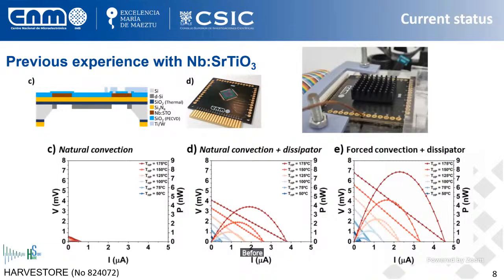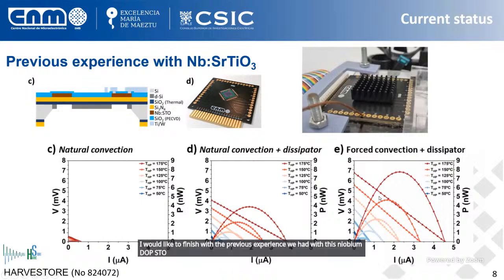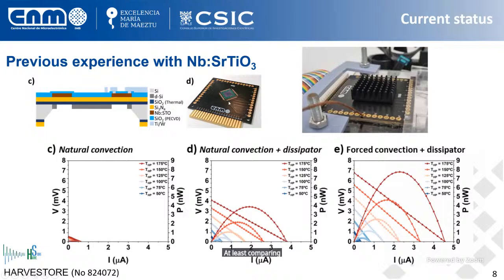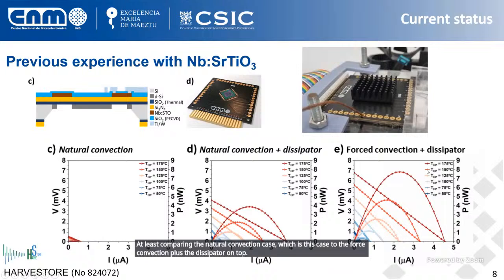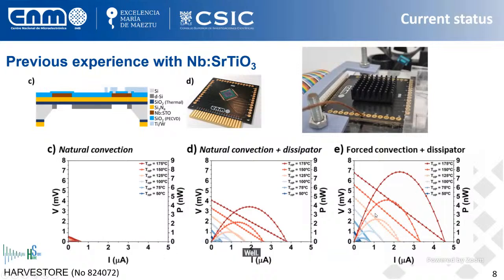I would like to finish with the previous experience we had with this niobium-doped STO. We already have measurements of this platform integrated on a PCB and with a heat exchanger on top, and we can see that the performance is increased by a factor of 10 at least, comparing the natural convection case, which is this case, to the forced convection plus the dissipator on top, where we can see that the performance is much more increased.